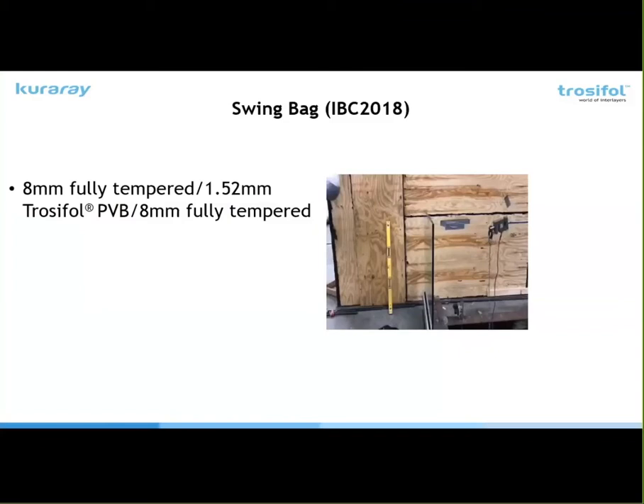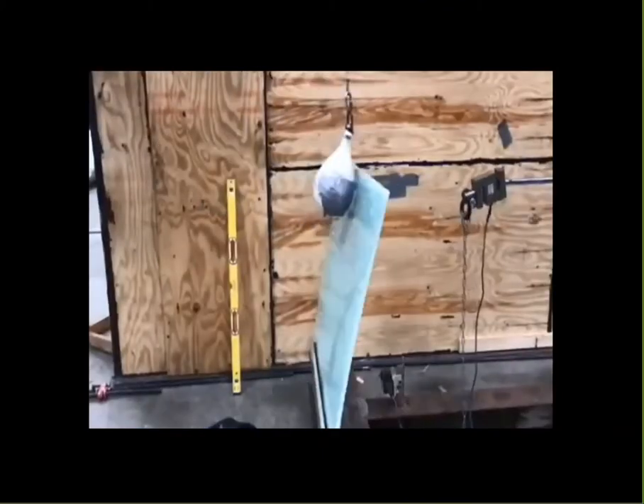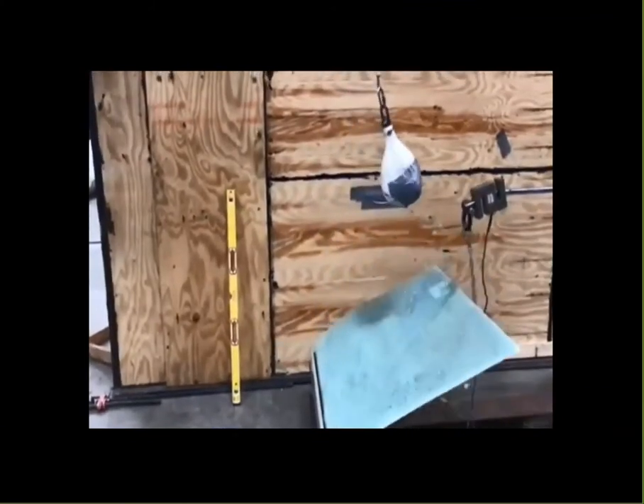So going from IBC 2015 to 2018, the change occurred in how you could install a railing without a metal cap or without railing connecting three pieces of glass. In IBC 2015, if you wanted to install a system like that, it required building official approval. In IBC 2018, it requires the system to be tested and the glass to remain in place, and it goes by ASTM E2353. So we've started doing some testing on the glass, and the previous videos were with 6 millimeter glass. This is 8 millimeter glass with the 60 thousandths Trosifol PVB, and after impact does exactly the same thing that the thinner glass did. It falls over like a wet blanket.